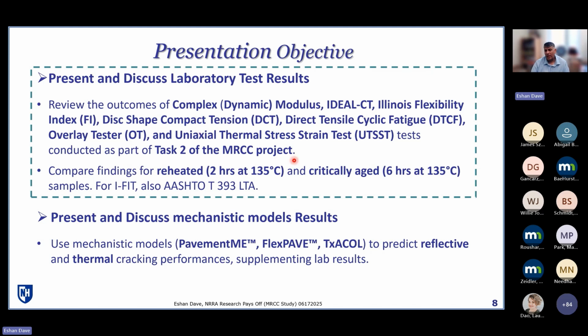And also we wanted to have some baseline information that we can use in models such as complex or dynamic modulus and so on. Also keep in mind that all testing was done with at least two different conditions. One is just a reheated condition, and one is a condition that is often referred to as critically aged condition, which for this location, based on the cumulative degree days, would be 6 hours at 135 degrees Celsius of loose mix aging prior to compaction.